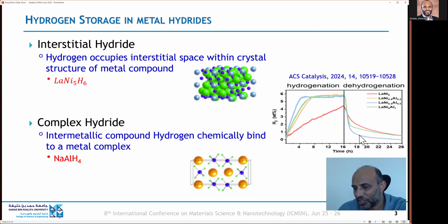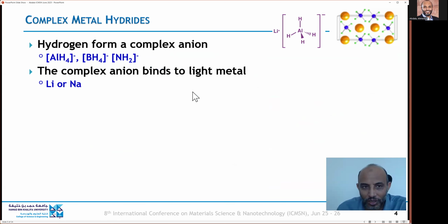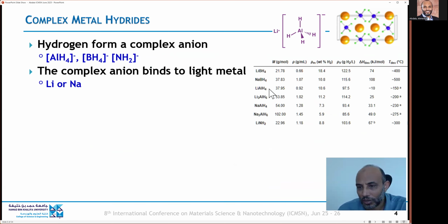But of course, the dehydrogenation, or the release of hydrogen from the metal hydride, the desorption, is quite a slow step. It requires more than 24 hours. So the challenge usually is associated with the release, which requires high temperature and also has slow kinetics. Examples of the complex metal hydrides have an anion complex of hydrogen with aluminum, boron, or nitrogen. And then this anion is complexed with a metal cation, either lithium or sodium.